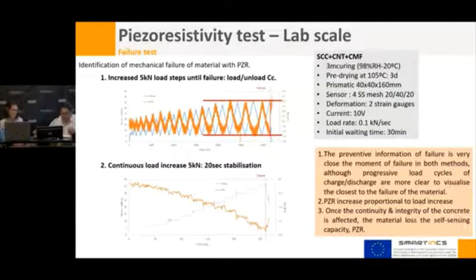Probably a consequence of some permanent deformation in the concrete. After loads of 38 megapascals, the sample failed, and the fractional change in resistivity caught the signal with a sharp drop.